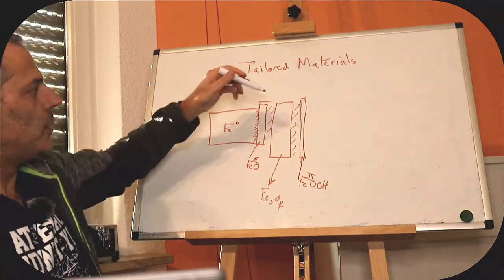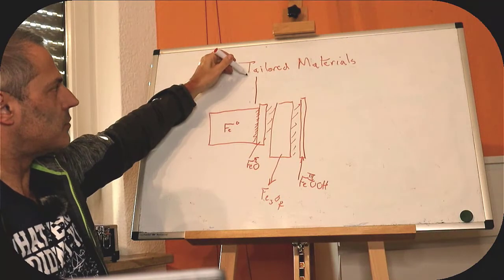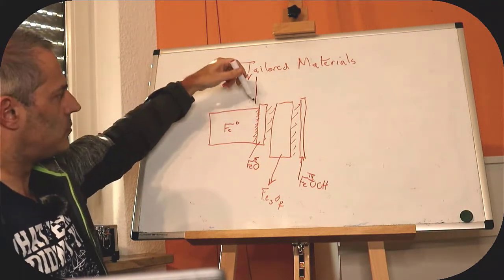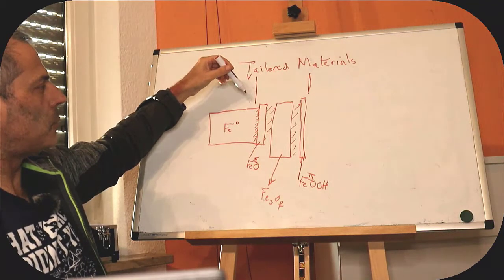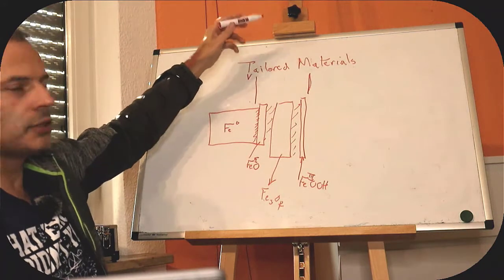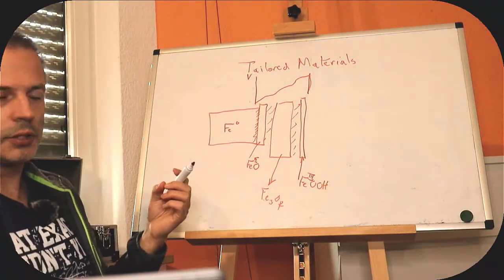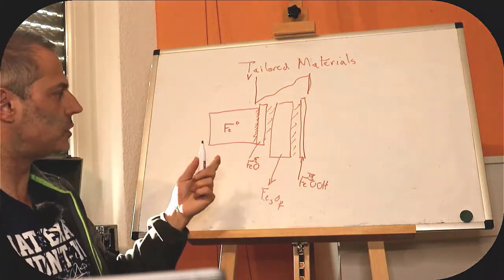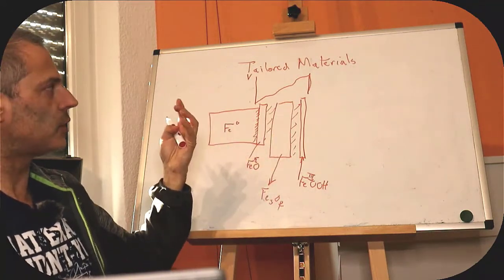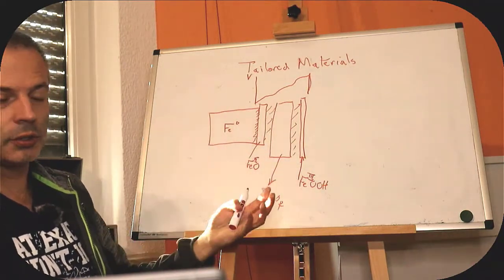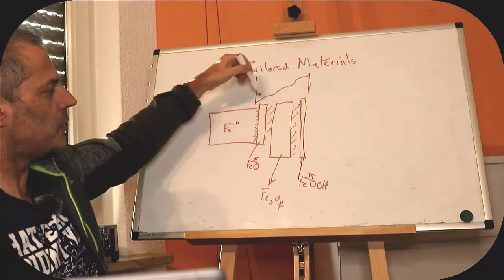What does this all take us to? Let's have the vertical axis as the voltage. And we consider this to be the surface, then we can imagine that the voltage, oxidation is near, just have oxidation up at the top. So then we can consider there to be some kind of profile of voltage from our iron, which is trying to hold the voltage at the iron naught, iron two couple. And the outside, which is the oxygen in the air, trying to hold the voltage at the oxygen to oxygen reduction reaction couple effectively.